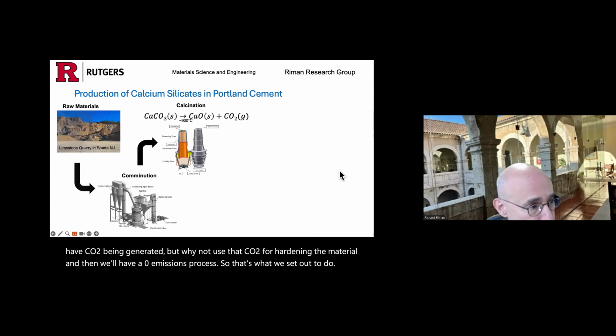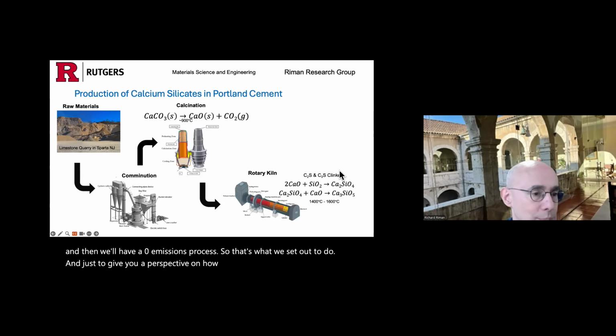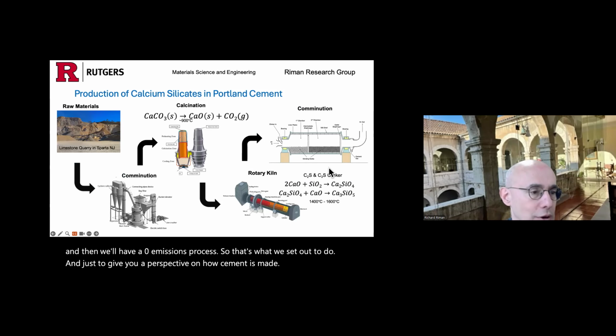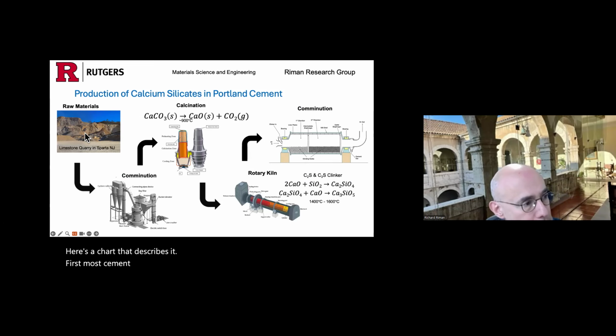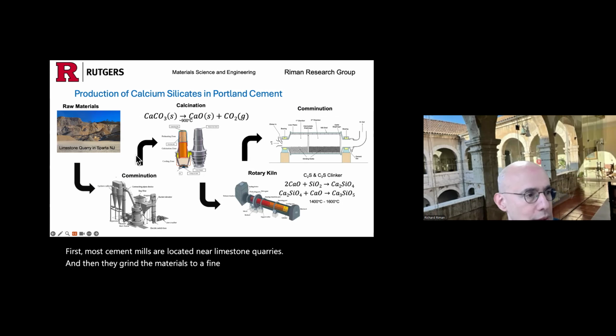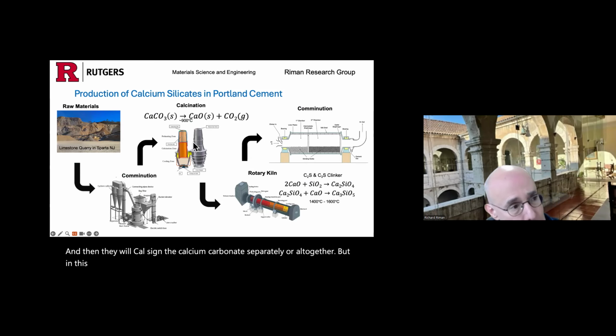And just to give you a perspective on how cement is made, here's a chart that describes it. First, most cement mills are located near limestone quarries. And then they grind the materials to a fine size. And then they will calcine the calcium carbonate separately or all together, but in this case, it's separate, at about 900 degrees. And then they'll do a reaction with the calcium oxide and the silica to make the cement product.